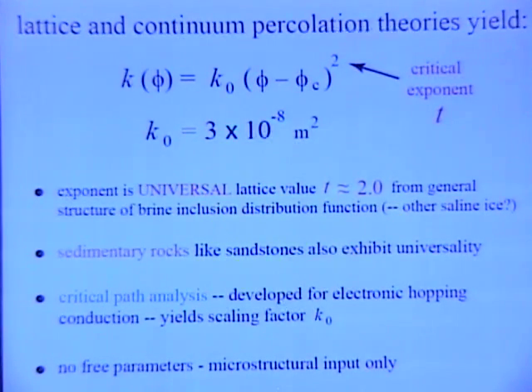kinds of distributions that we have for the brine inclusions in sea ice, we can conclude that even though in the continuum you can get so-called non-universal behavior with non-standard critical exponents, in sea ice we should be seeing, amazingly, the universal lattice value of about 2 in 3 dimensions, which again is something I did a lot of work on earlier in my career.